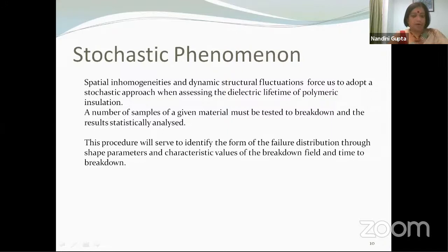So therefore, it is very important that we adopt a stochastic process, which means that we must have a considerable number of samples of a given material. We must evolve test procedures so that we can get statistical estimates, and these results have to be statistically analyzed. When I talk about testing a number of samples, how many? That is in the realm of statistics. We need to look at population samples, how to build population samples, but we also need to remember that in this case, we are looking at destructive degradation, and therefore the ideal situation is not something that we can adopt. We might have to compromise. And then once these tests are done, the procedure would be to identify the form of the failure distribution. What do I mean by failure distribution?